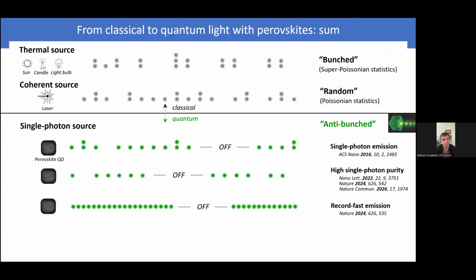So the only faithful alternatives to lead are tin, which is a very good choice. So Dmytro, I would say tin has future. The only problem with tin is instability. Tin and germanium, but germanium is way worse. Tin is a good alternative, but tin 2 plus is very unstable against tin 0 and tin 4 plus. And that would be okay, but on top of that, tin-based perovskite have very low formation energy for tin vacancies, and that leads to self-doping of p-type.